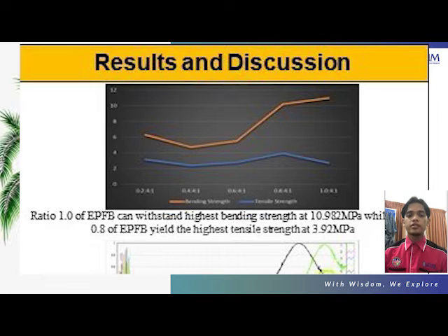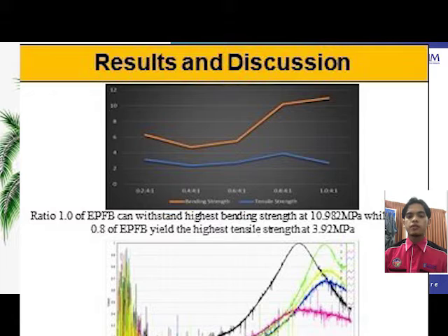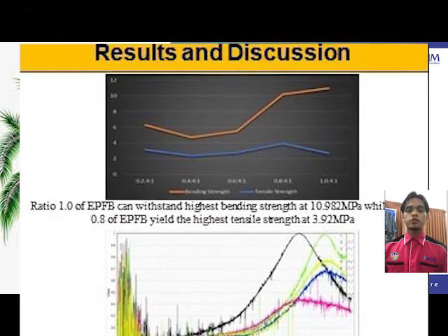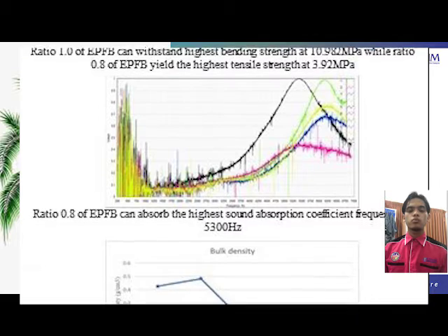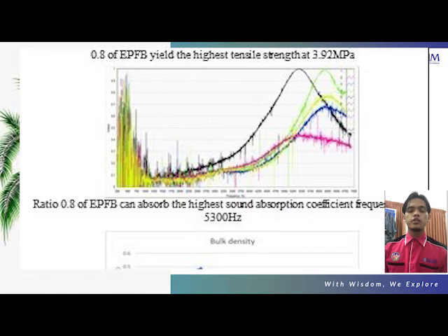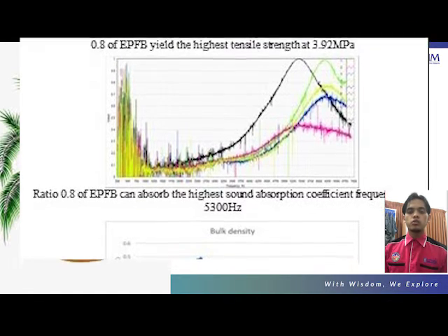For tensile test, we can see that the highest tensile strength is yielded by the ratio 0.8 of EPFB with 3.92 megapascal, followed by the ratio of 0.6 of EPFB with 2.79 megapascal. For sound absorption test, the sample that can absorb most sound at high frequency is the sample with the ratio 0.8 of EPFB with the 5300 Hz of the sound absorption coefficient, followed by the 1.0 ratio of the EPFB.